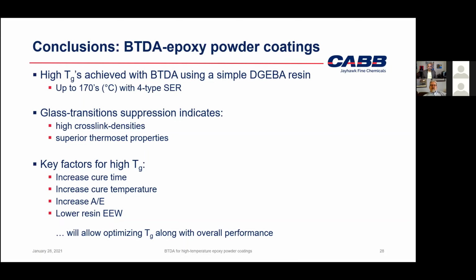And we've demonstrated the fundamental behavior of BTDA with the pretty straightforward epoxy type resins. And you can see the behavior and how you can navigate into getting higher T sub Gs for sure. We didn't do a lot of other testing. We know that higher TGs are going to give you certain performance features that go along with it: heat resistance, chemical resistance, and things like that. Maybe a loss in mechanical performance like flexibility and elongation, but at the same time more hardness and abrasion resistance.